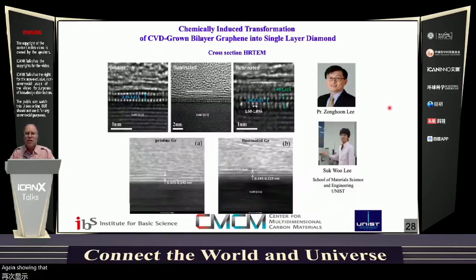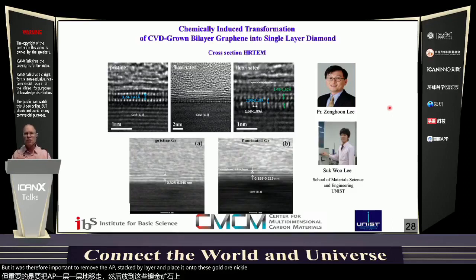Again, showing the cross-section TEM, so I won't delve too deeply into this. I think it's very important to mention to our audience that we not only made the fluorinated diamane on the metal film. So earlier I showed you a theoretical calculation that suggested the bottom graphene layer could chemically bond to the metal. But in our case, that didn't happen. The fluorine actually went down into the copper nickel. We have a variety of different evidence of that. And so the film had fluorine at the interface that converted the bottom layer to the fluorination CF bonding. But it was therefore important to remove the AB stacked bilayer and place it onto these gold or nickel grids, which can withstand exposure to xenon difluoride, to fluorine.